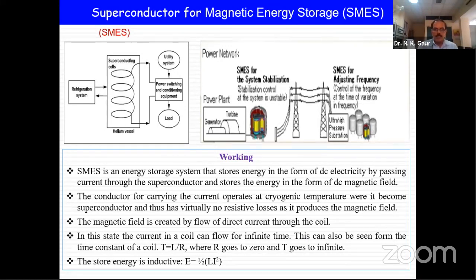This can be seen from the time constant of a coil, that is T is equal to L by R. If R goes to 0, that is in the superconductor, if we take the superconducting coil, the resistance is 0. If resistance is 0, that means T is infinite. And the stored energy is inductive also, E is equal to half Li square.